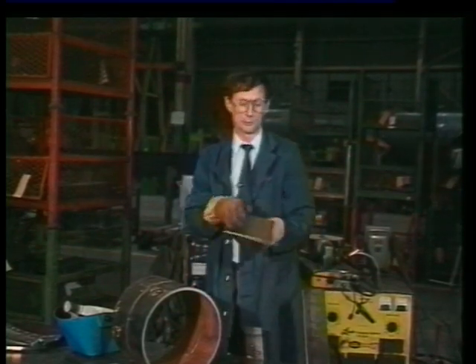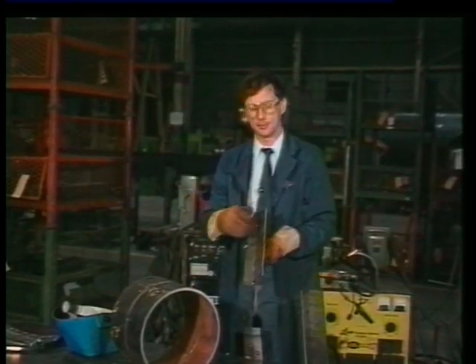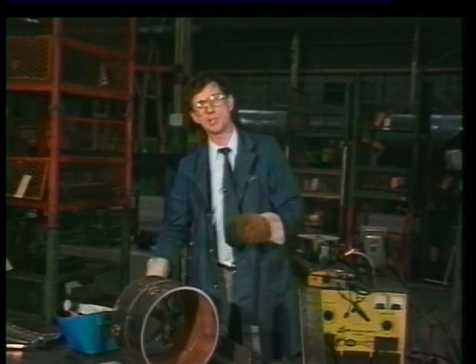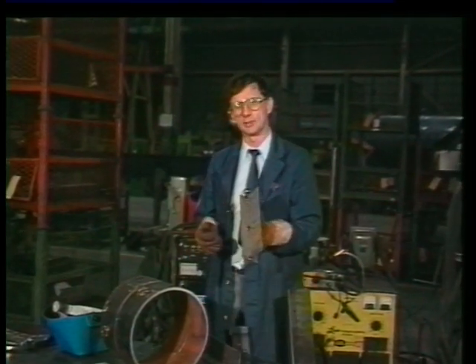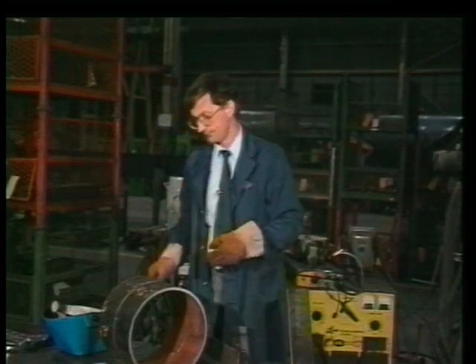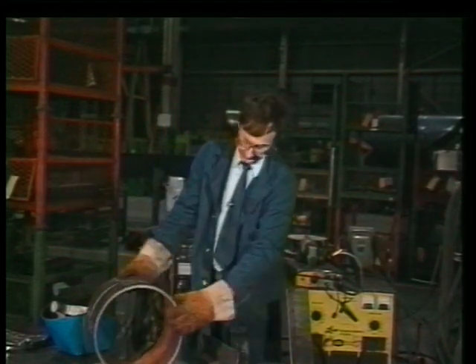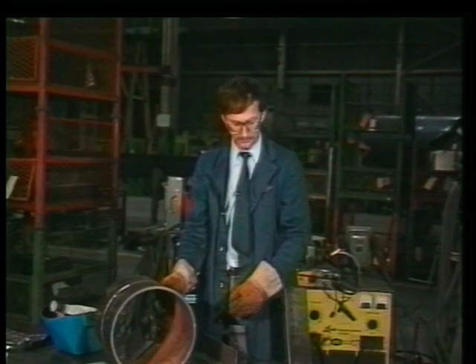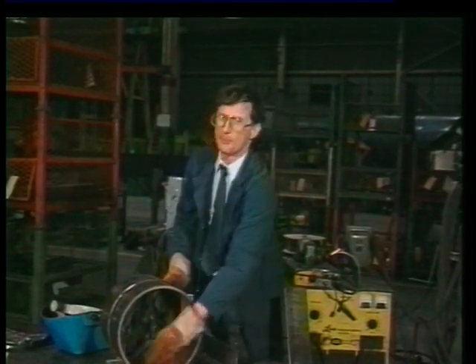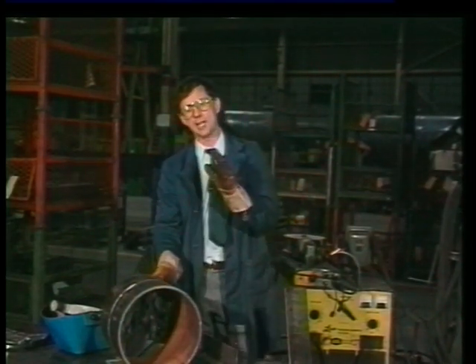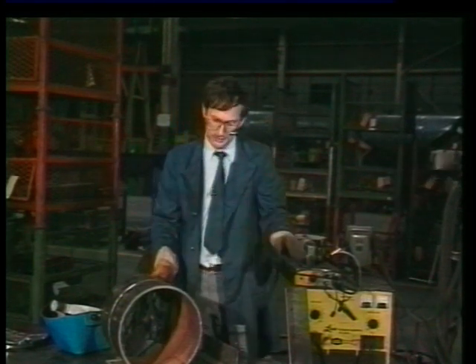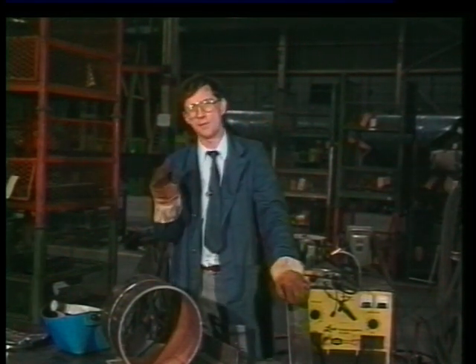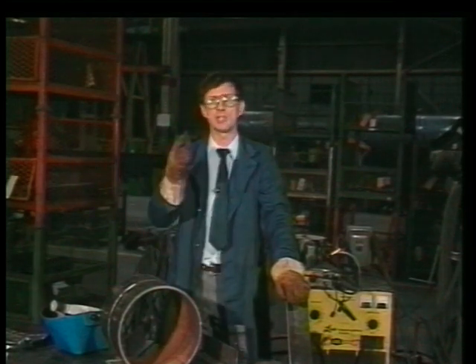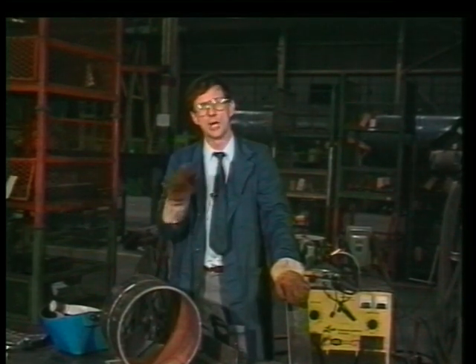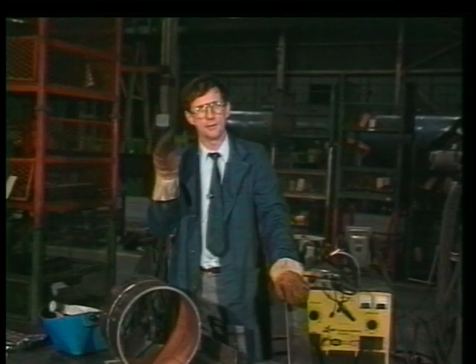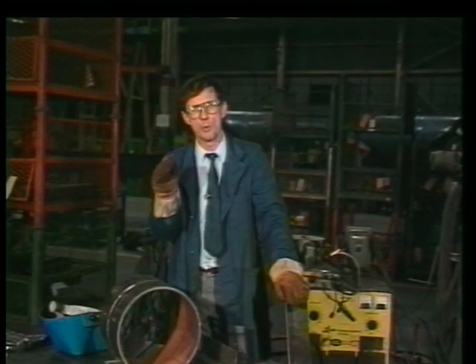Applications like 10 gauge plate, vertical up. Applications like 16 gauge material, fillet weld. How about a root pass in a pipe? These are basically short circuiting applications. Remember, the simple rule is if it's less than an eighth of an inch, or it requires vertical up or vertical down, or you're welding a gap, you simply think of short circuiting welding.